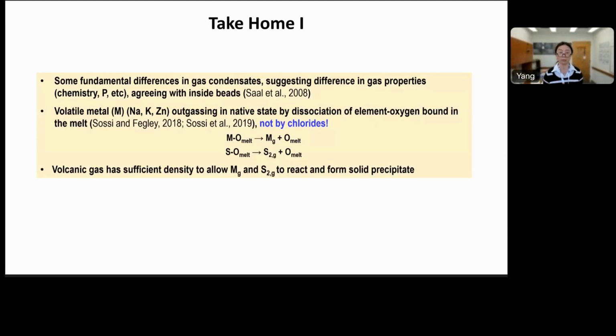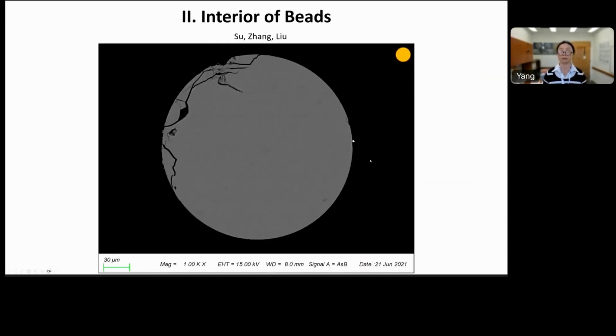The volatile metals outgas from the lunar magma not as chlorides, but through processes involving multiple reactions. For example, sodium in the silicate melt would first be outgassed as a metal phase, through dissociation of the oxygen bond in the melt, and so is sulfur. Then those native state elements in the volcanic gas will react and form the solid precipitates. This also has implications when we do isotope modeling in terms of how the isotopes would evolve, because it's not a same-species type of modeling.